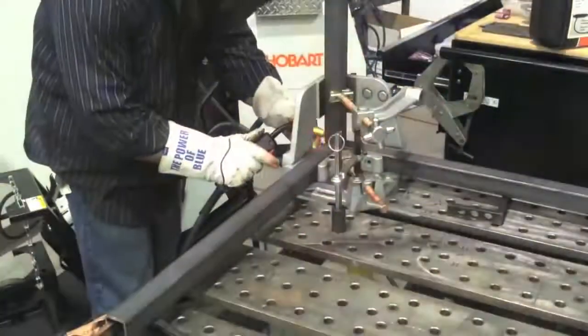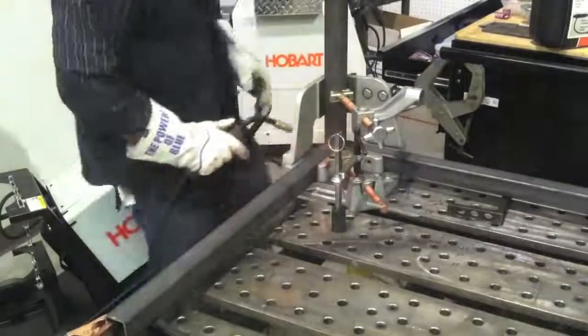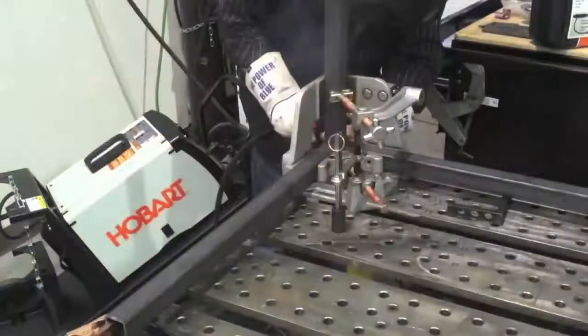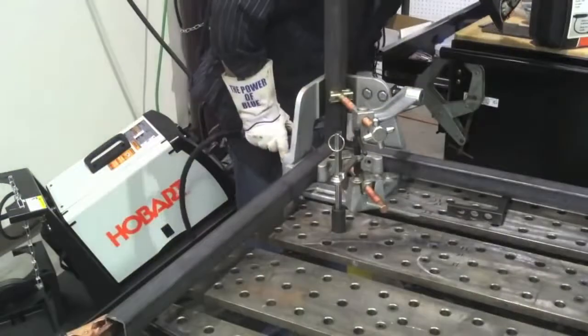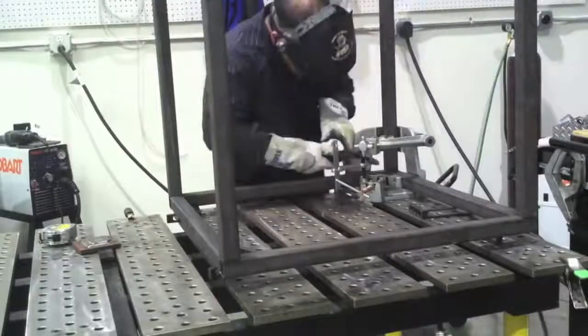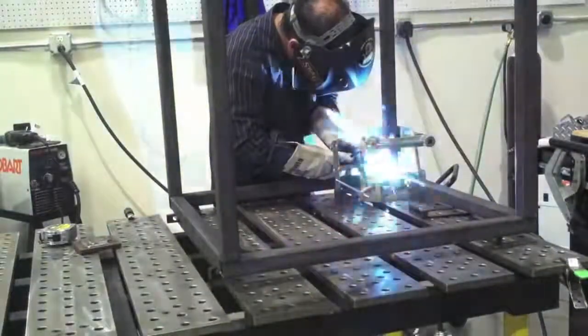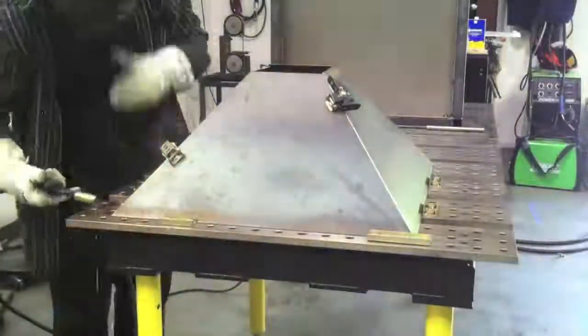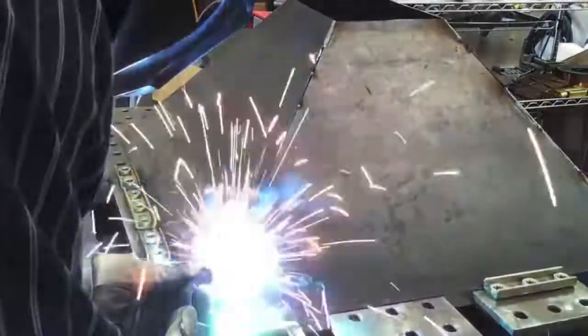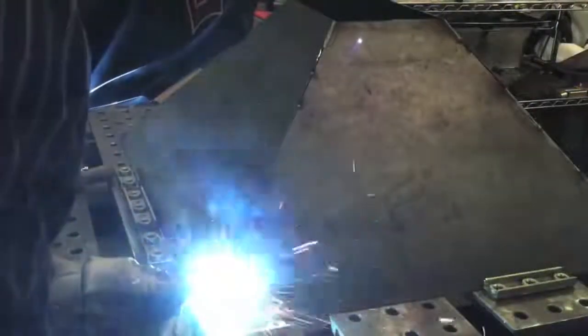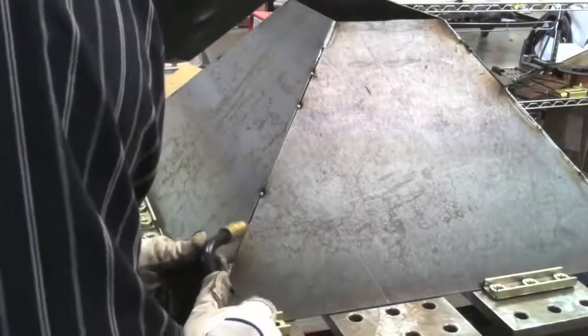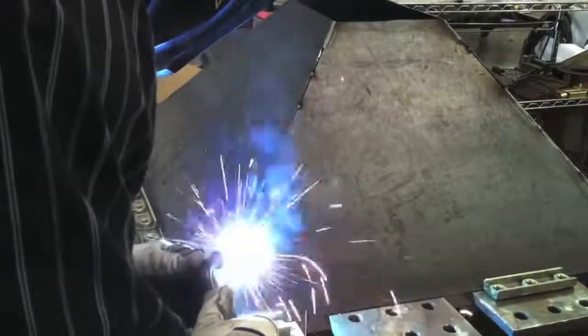Here I am using that Hobart 210 MVP, and it's just a little light fabrication job with 1.5" square tubing, 1/8 wall, doing a whole lot of tacking, and then when this frame gets tacked all up, it gets welded up. But I'm only going to weld 1.5" at a time before I reposition, so the machine gets a lot of time to rest. Now here, sheet metal fabrication, a lot of tacking. Even though it's a lot of welding, it's at really low amperage, like maybe 50 or 60 amps. So having a 30% duty cycle at 150 amps, not a problem. A job like this can easily be done with a 115 volt MIG welder with a fairly low duty cycle.